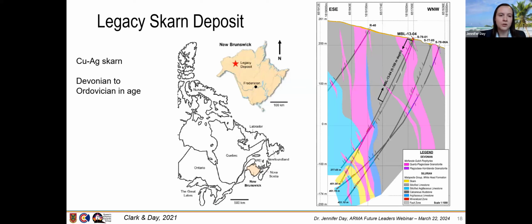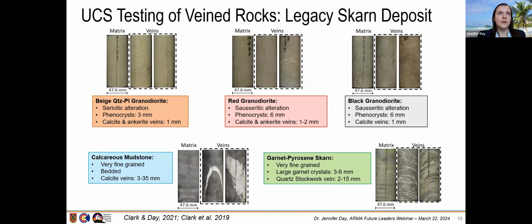You can see the section of one of the boreholes we looked at, NBL 1304, that goes through a couple of different lithologies. The UCS testing that Matt did involved 5 lithologies from the Legacy skarn deposit. There are 3 varieties of granodiorite: a beige, a red, and a black. And then we've got a calcareous mudstone and the garnet pyroxene skarn. For the veins within these rocks, all of the granodiorites had calcite and ankerite veins that were fairly narrow, about 1 to 2 millimeters. Some of these samples also had some phenocrysts in the matrix.